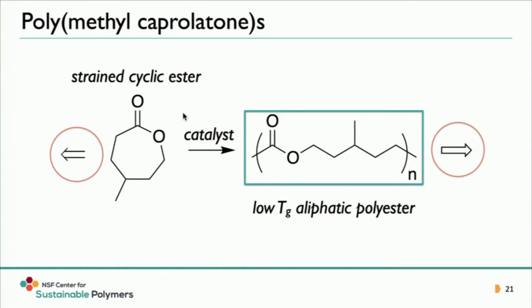But that's a strained cyclic ester that, through catalytic action, can be turned into this low glass transition temperature aliphatic polyester. And what that means is just the softening point of this material is at very low temperature, so it remains flexible at ambient and even subambient temperatures. So I'm going to talk a little bit about how to make this conversion in a green way, but I also want to talk about its origins and also the fate of polymethyl caprolactone containing materials.